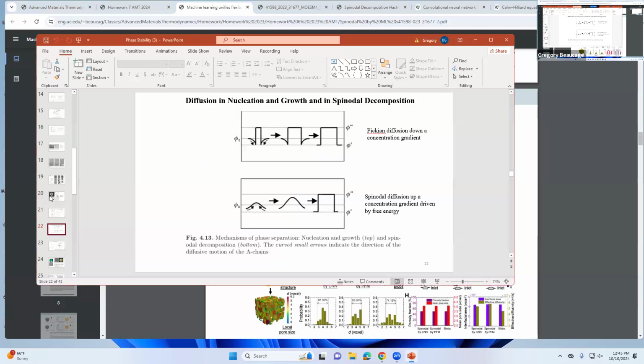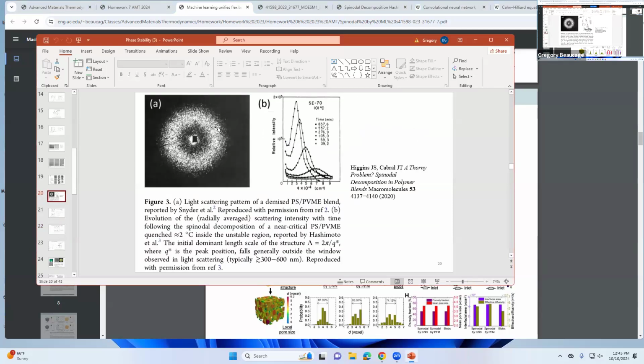So they should have a fairly close to monodisperse phase size, and also close to monodisperse spacing of the phases, which gives rise to this scattering pattern if you shoot a beam of light through it, which has a ring. So you have your sample, shoot a beam through it, collect the pattern on a piece of paper. The main beam is in the middle, and then the angle of scattering is from there to there, and that's the size of your spinodal structure that's forming.